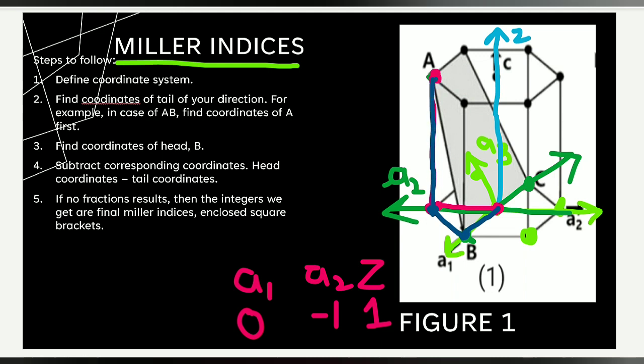That was another path that was possible, but the problem with that path is that though this direction, this one, I hope you can see, was positive, along A1 direction, and that is permissible, but this one motion onwards was along A3 direction, which is not permissible. Okay, it is not permissible at all. As I told you people, movement along A3 is prohibited while finding out Miller indices. So that is why I didn't take that path to find out the coordinates. I took the path in which I have to move along A2, Z or A1 direction, but not along A3 direction. So all paths that involve movement along A3 direction will be cancelled out, and we have to shorten down to those paths that involve motion along A1, A2 and Z direction. So that was one of the examples.